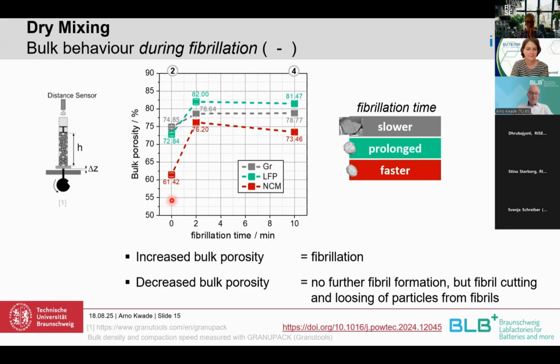Looking at the bulk porosity for these different materials, you see that there are quite some differences. After the fibrillation, all have an increase in the bulk porosity, so the volume of the overall powder increases. But there are some differences in the porosity. The LFP has the highest porosity, the NCM the lowest porosity.